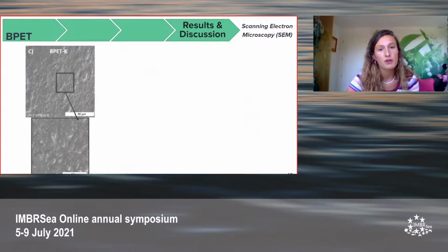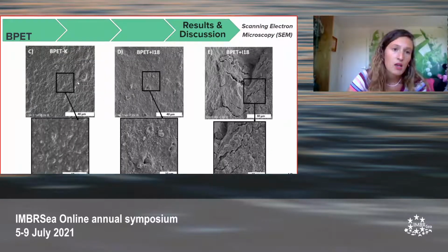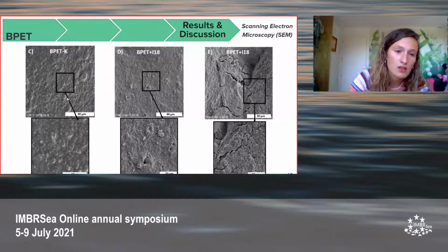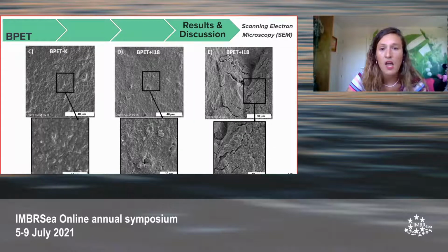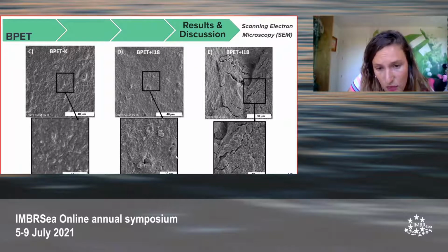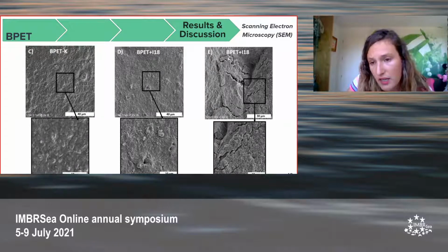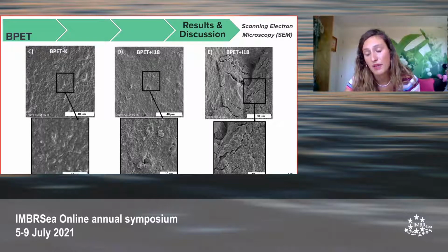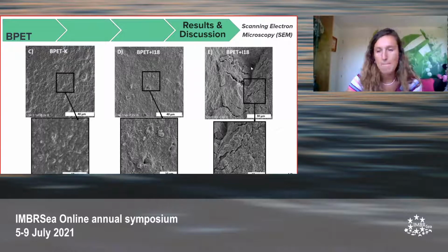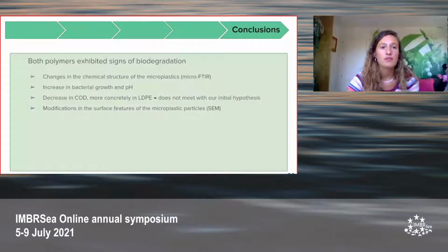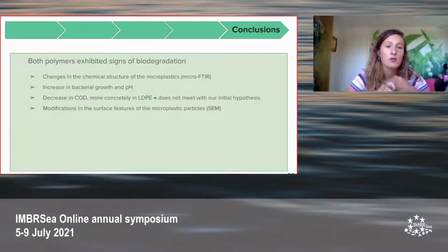In the case of biodegradable PET, similar results are obtained, in which the control particle surfaces are smoother with no bacteria, whereas in the ones with inocula, we can see all the bacteria attached with holes, and here is a clear example of a bacterial biofilm, and these are all indicative of polymer degradation. So to conclude, we must say that both polymers exhibited signs of biodegradation because we saw some changes